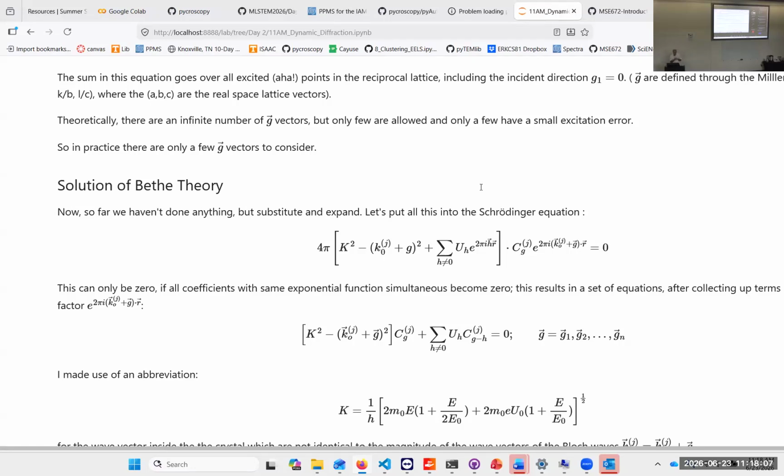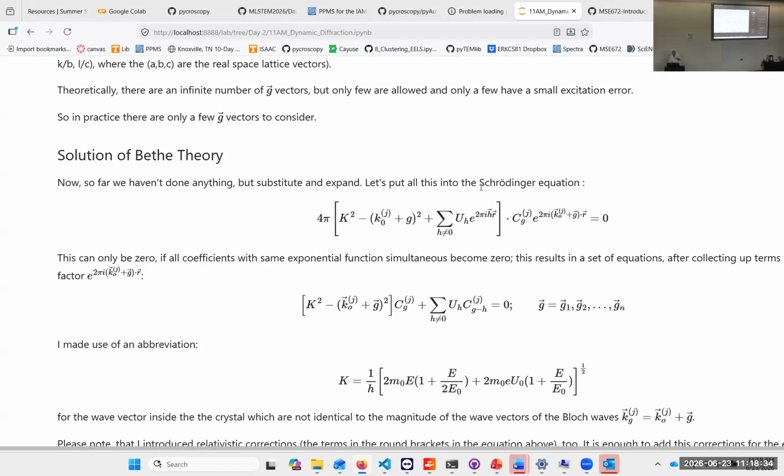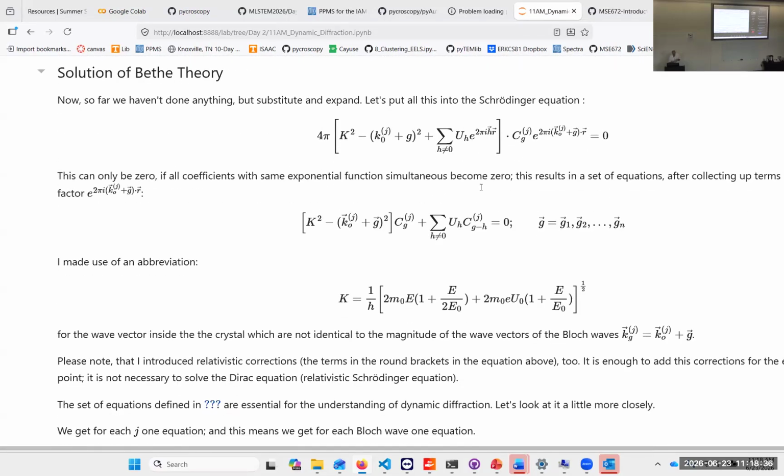And so if we are looking in a high-angular dark field detector, on the atomic column it's bright because we scatter a lot. We'll come to that in a moment. And in between of them it's dark. So in a way, what we do is a near-field technique where we select the one Bloch wave over the other Bloch waves. So that's what we are trying to do here.